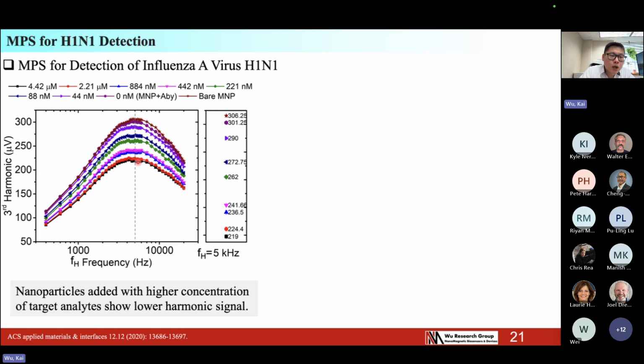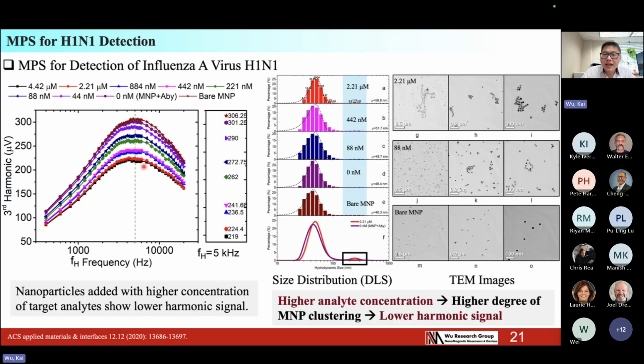You can clearly see that with higher concentration of the analytes, the harmonic signal will drop due to the bonding causing clusters, which will lower the dynamic response of particle, which will lower the harmonic amplitude of the third harmonic. We can also see from the TEM imaging after the MPS assay, the proteins will cause the clusterings of nanoparticles when there's a high concentration, 2.2 micromolar concentration of the proteins in the solution.